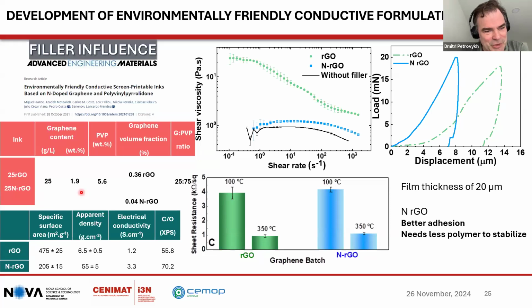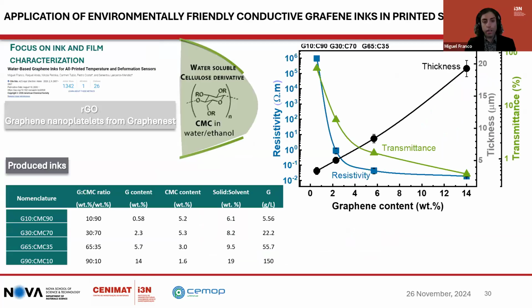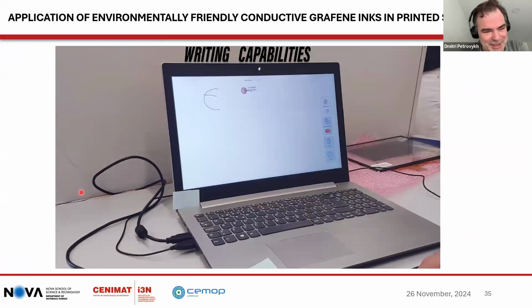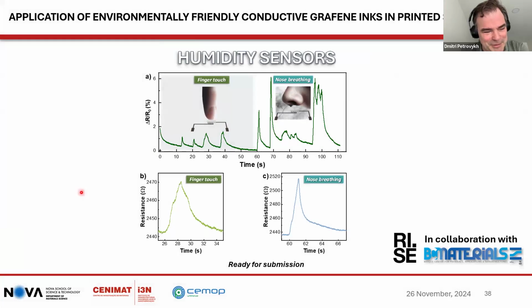You mentioned using the humidity sensor to detect a touch. Is that based on the humidity or the small amount of water on the tip of the finger? How was the detection working? In this case, the small change of resistance is due to the presence of water itself, not the pressure. So this relies on having a little bit of sweat or some other water on the finger. I guess if it's really cold or really dry, then it may not work as well. Yes, exactly.